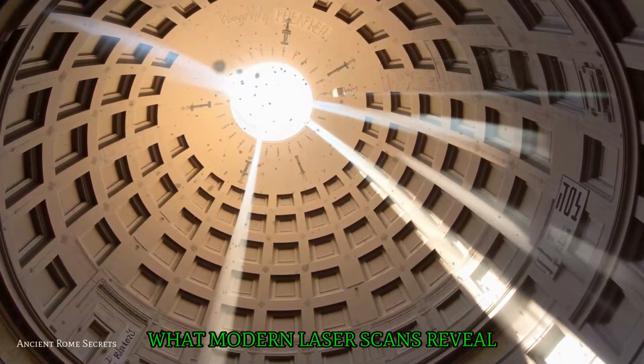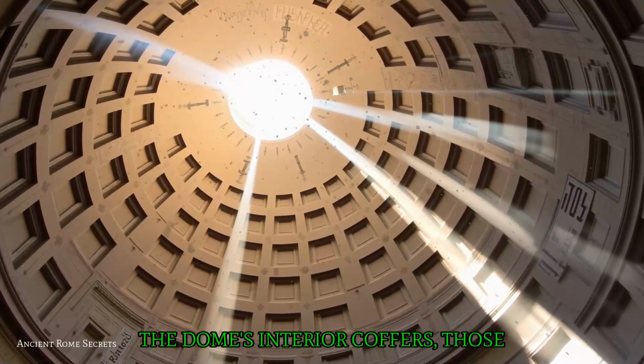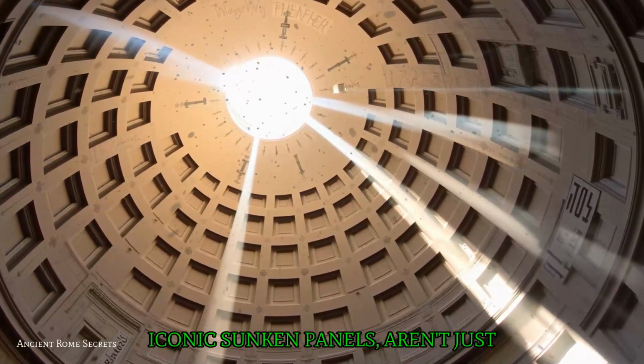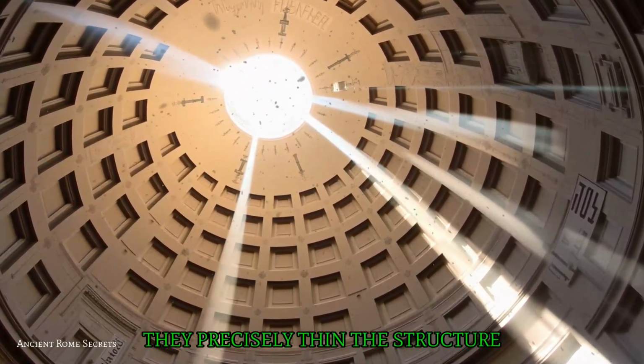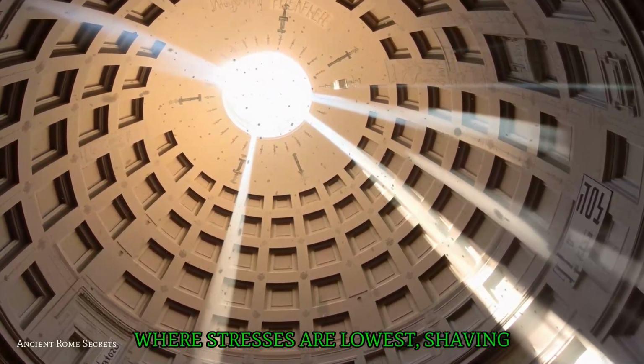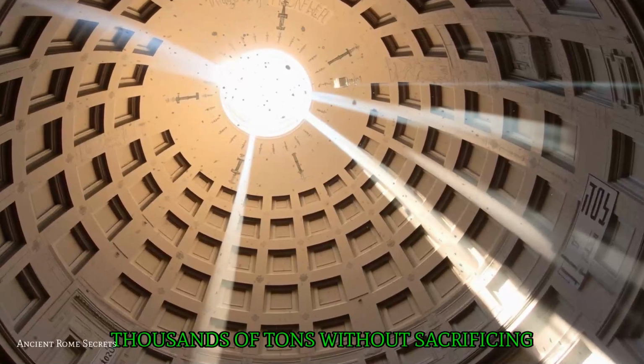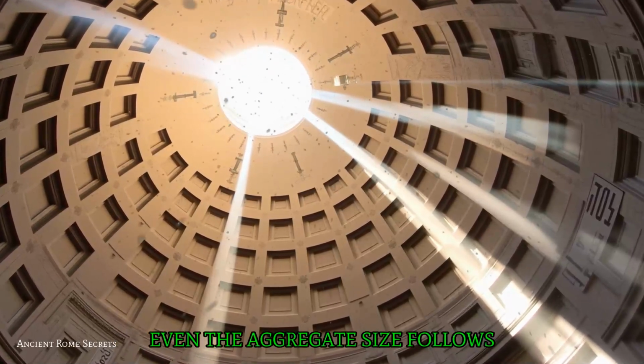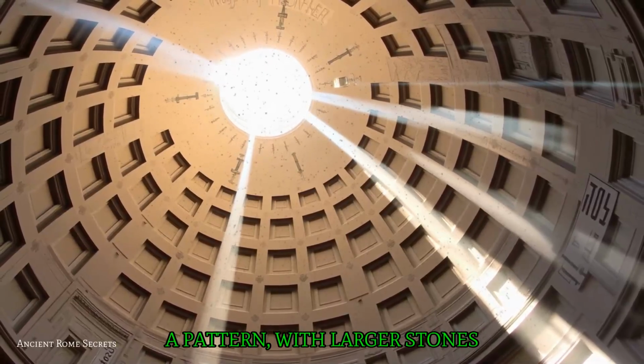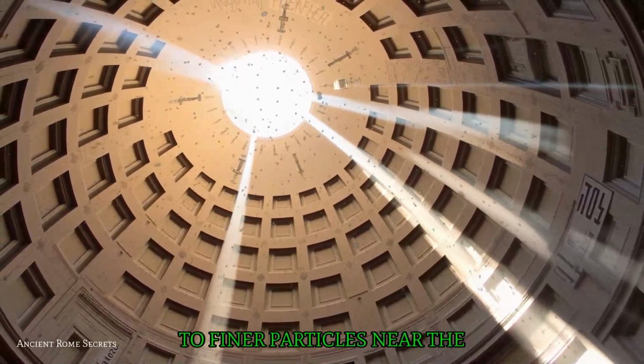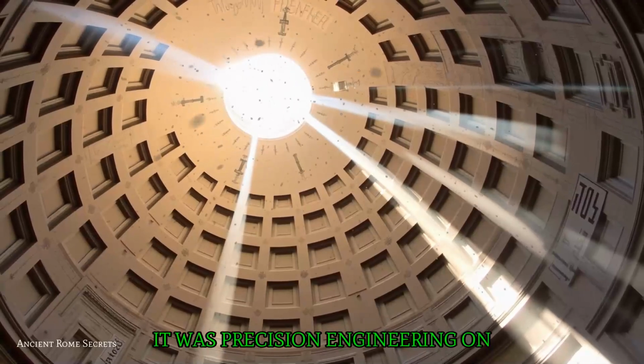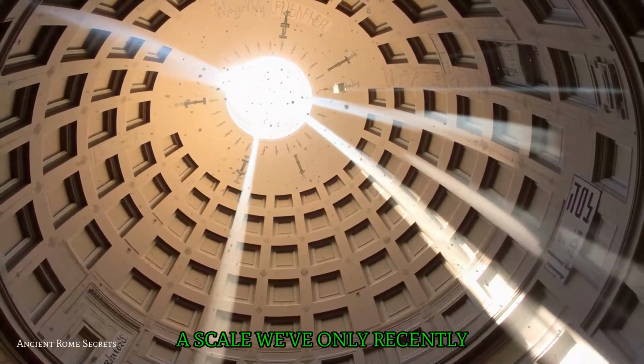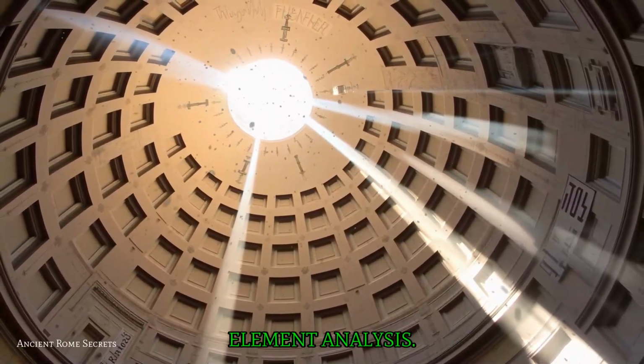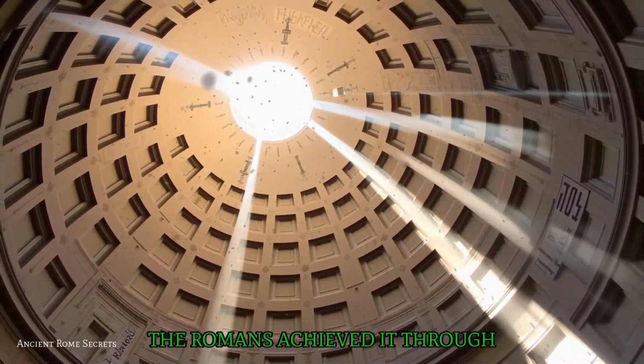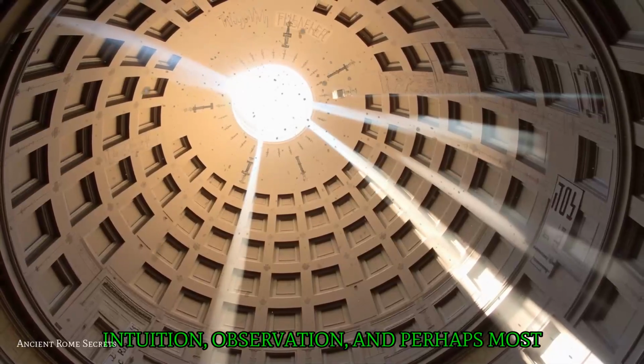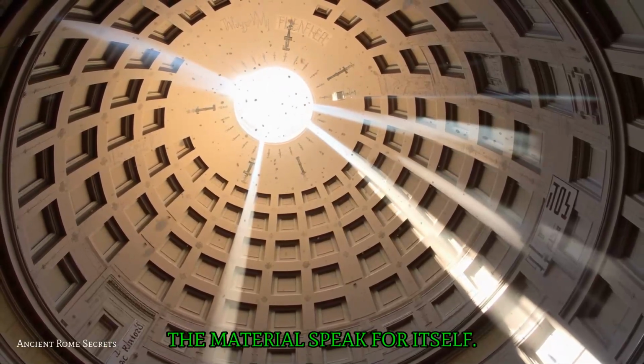What modern laser scans reveal is even more extraordinary. The dome's interior coffers, those iconic sunken panels, aren't just decorative. They precisely thin the structure where stresses are lowest, shaving thousands of tons without sacrificing integrity. Even the aggregate size follows a pattern, with larger stones at the base giving way to finer particles near the top. This wasn't guesswork, it was precision engineering on a scale we've only recently begun to quantify with finite element analysis. The Romans achieved it through intuition, observation, and perhaps most importantly, a willingness to let the material speak for itself.